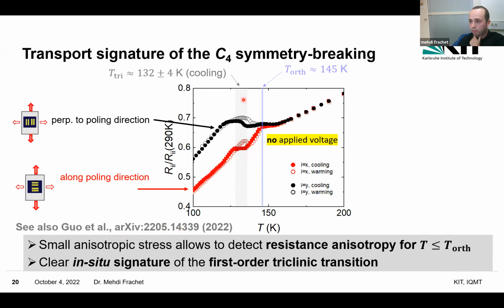The second thing I want to mention on this figure is that you see a clear thermal hysteresis, which is an in-situ signature of the first order triclinic transition, which allows us to pinpoint the triclinic transition on the piezo actually.